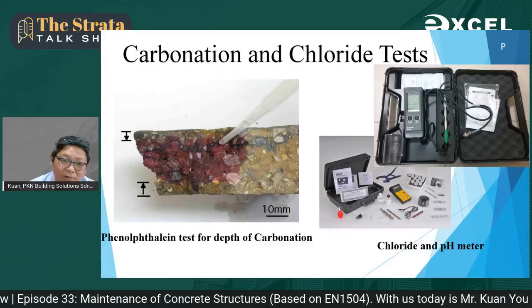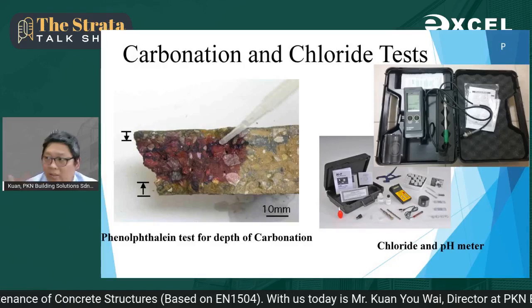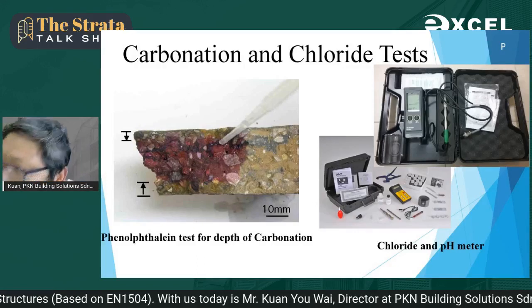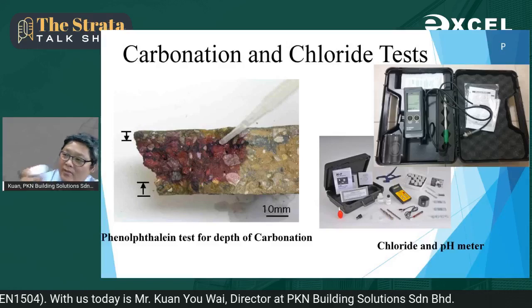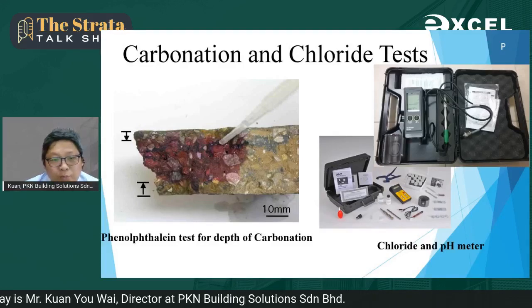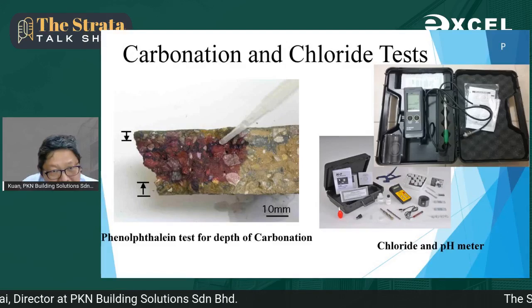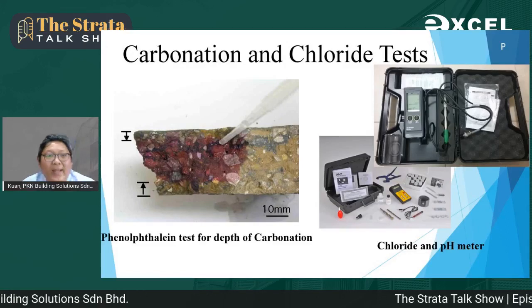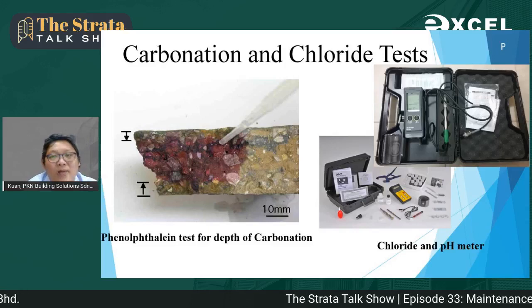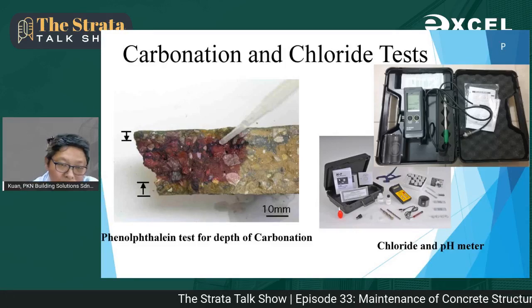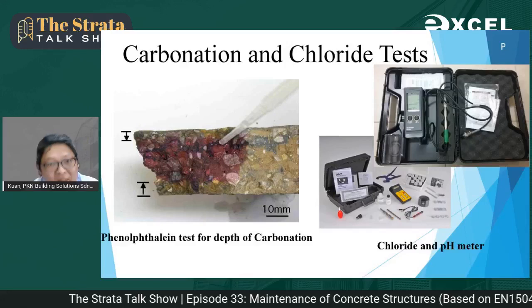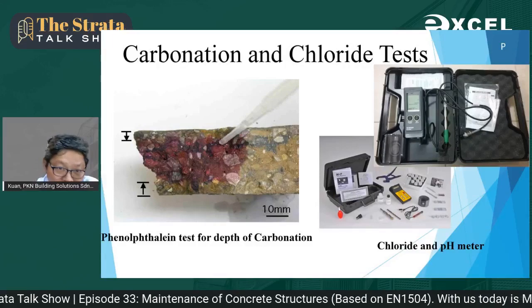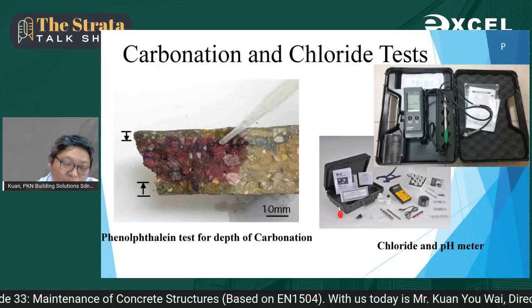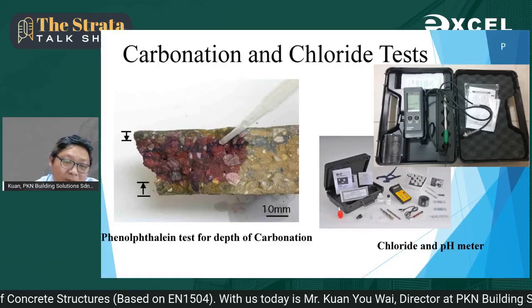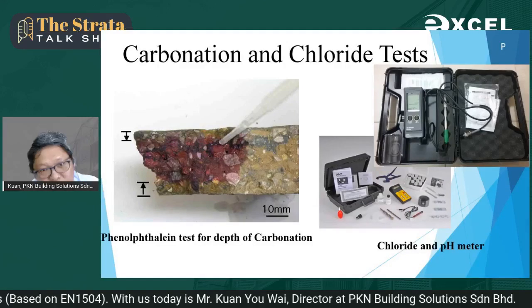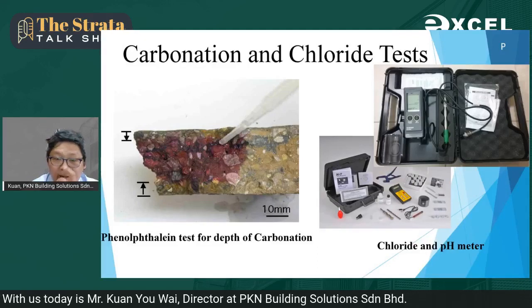And the carbonation level. Phenolphthalein liquid. Okay, I have some here. This is phenolphthalein liquid. If I spray it on the concrete, anything with pH less than 9 will become transparent. pH more than 9 will become purple in color. So I can see exactly what the depth of carbonation is. And of course, the most important part is whether the carbonated concrete has reached the reinforcement steel bar. So this is a very convenient and economic way.